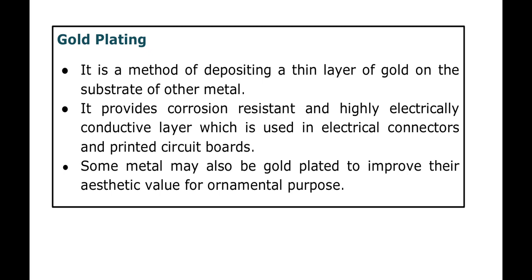The major problem in gold plating on copper is that copper atoms have a tendency to diffuse through the gold layer, causing tarnishing of its surface and formation of an oxide or sulfide layer. To avoid this, a layer of a barrier metal like nickel is applied before the gold plating on the copper substrate, as nickel atoms do not diffuse into gold.